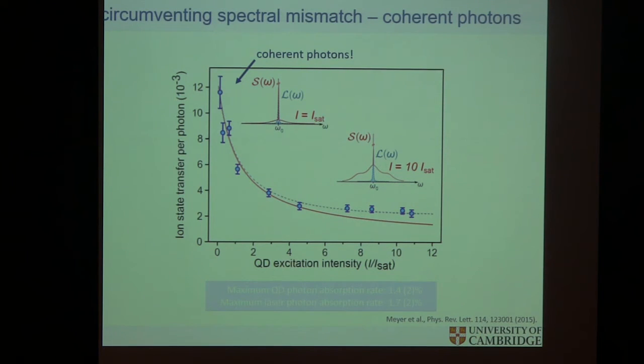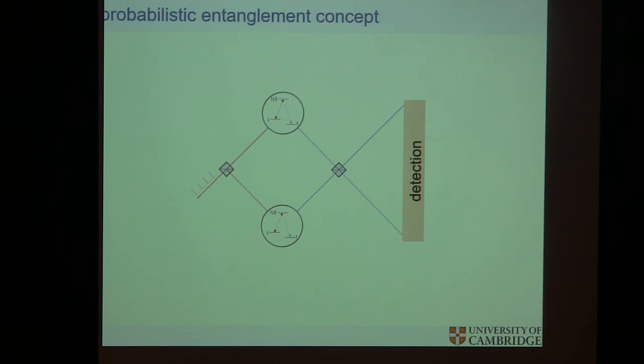So if I were to take a single laser and drive the ion, I can see the transitions, I can saturate the ion. If I do the same thing with single photons from a quantum dot, we could also saturate the ion, even though the spectra don't match at all. So that's where immediately you can think of using these coherent, elastically scattered photons to link multiple systems. Okay?